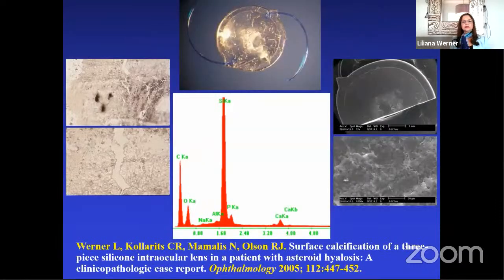This case was interesting because the patient had bilateral asteroid hyalosis. One eye was implanted with this 3-piece silicone lens, which exhibited calcification on the posterior optic surface and had to be therefore explanted. The other eye was implanted with a hydrophobic acrylic IOL that never calcified.